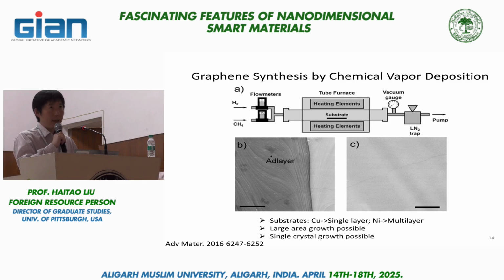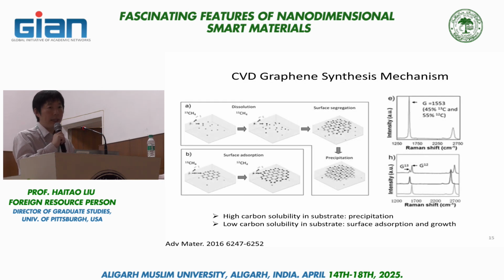People spend a lot of effort understanding this growth mechanism, and basically there are two different mechanisms in operation depending on what kind of metal substrate you are using. If you're using a metal that has a low solubility of carbon, copper being one of those examples, then the gas decomposition products from the methane gas, essentially the carbon radicals, will come to the copper surface and adsorb to the surface, but they cannot dissolve into the copper lattice. So they will stay on the surface, lose hydrogen, and be coupled to other carbon species. So this is an adsorption and growth process, shown as B.